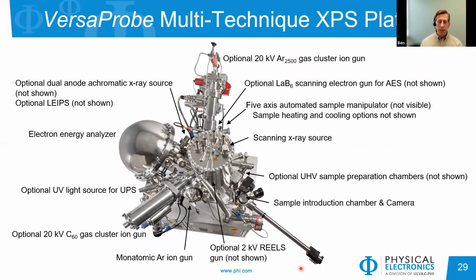We offer a C60 cluster beam, which is very useful for inorganic and organic mixed materials, which tends to be what a lot of these battery materials are, when you have the oxide, the electrode material, the electrolyte materials and whatnot. So that can be a pretty nice ion gun to use. We also have an argon gas cluster, which is very useful for fast sputtering of organic materials. And so what you may find is that your organic sputters much quicker, leaving behind a skeleton of inorganic, which may be useful to you to understand that.